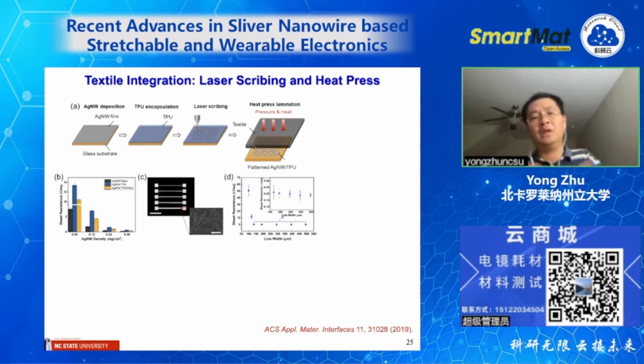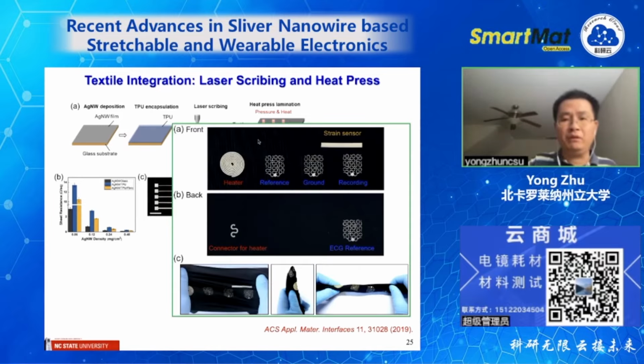The TPU here serves a dual purpose. One is it provides a stretchable substrate, but it also provides a structural adhesive. Under pressure and heat, it forms a strong bond with the textiles. Here I'm showing you a few devices. We printed this spiral pattern as a heater, and this fractal pattern for electrodes. For these electrodes, we print on the top and the back and so on. You can see this is the textile, very flexible. We can easily deform it.